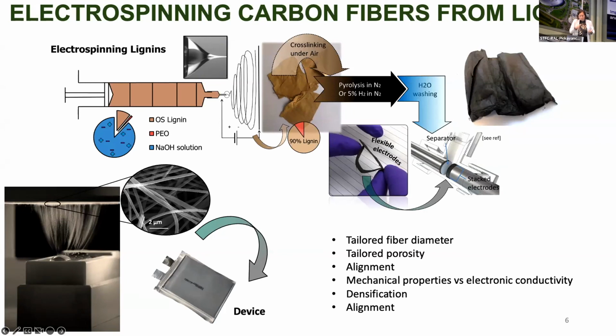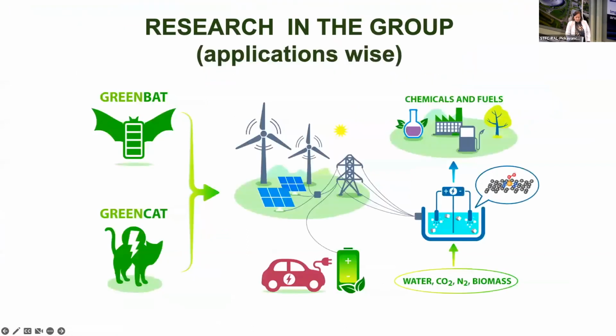We could make it with micropores, with mesopores, with no pores, with aligned fibers. We've stacked fibers together to increase the density. We can tune mechanical properties versus electronic conductivity. As I said, we can align them in different directions. And normally we use these freestanding carbon mats in energy applications, mostly batteries, to make structural electrodes that have no current collector.